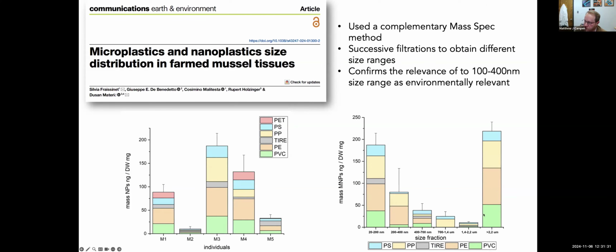But what was fascinating was they did a subsequent sequential filtration to look at the different sizes of particles, and what they showed was, yes, there was a fair amount of mass in some large particles, but from 20 to 200 nanometers and 200 to 400 nanometers were their largest bins for the total mass that they're seeing inside these sea creatures.